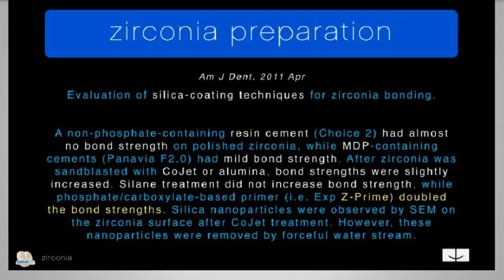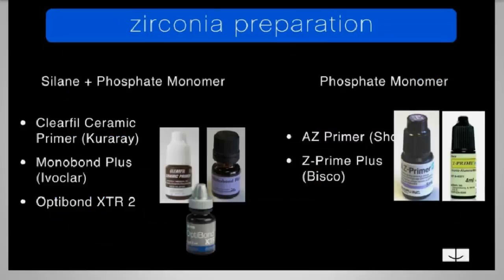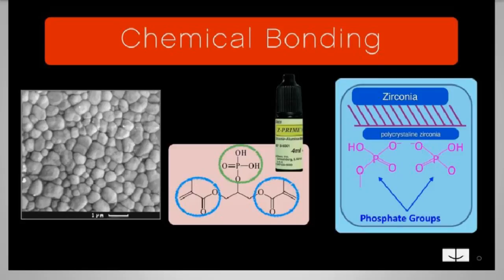But when using a zirconia-specific primer like Z Prime, bond strengths doubled. So there are a lot of them out there that say you can use it on zirconia, right? If it has MDP in the adhesive again, then I would say that's better. But there's AZ Primer by Shofu and Z Prime Plus by Bisco. Those are the really, really good zirconia-specific primers. And again, that's what I use.